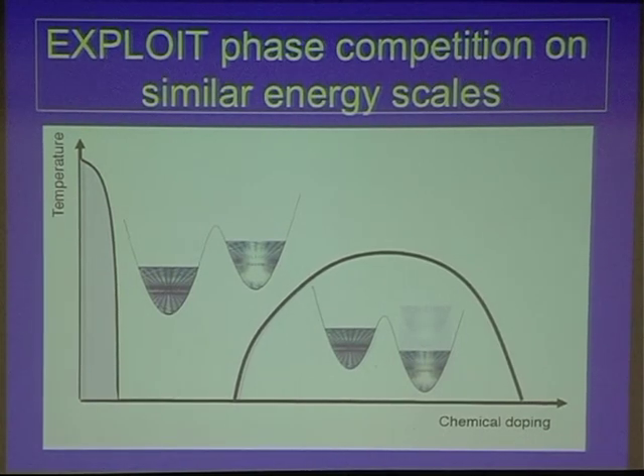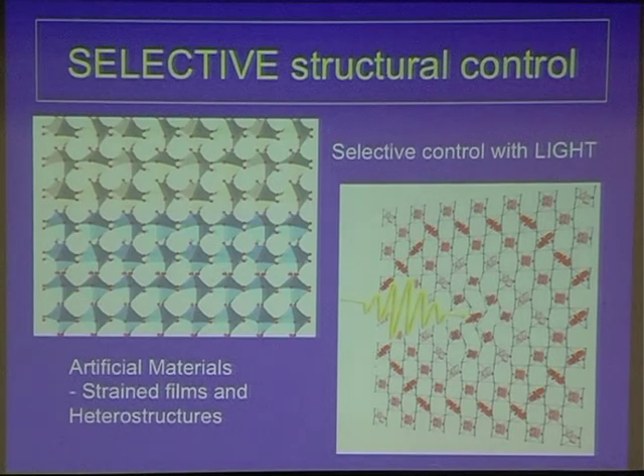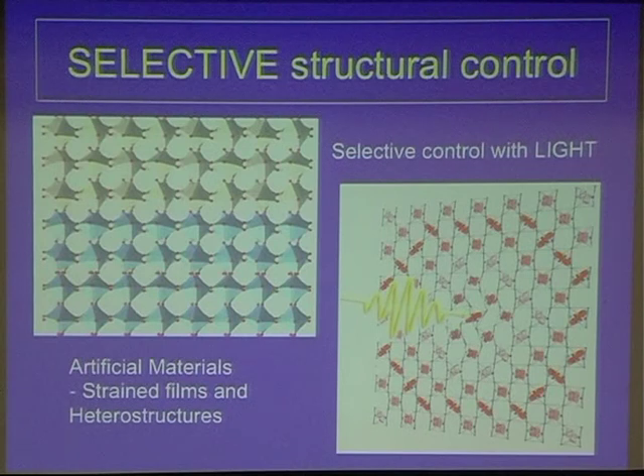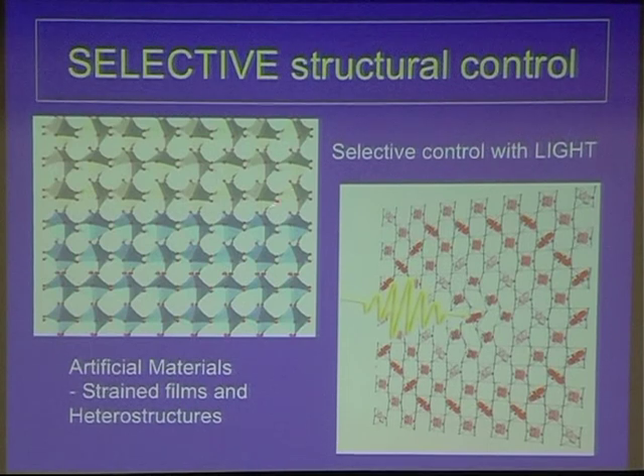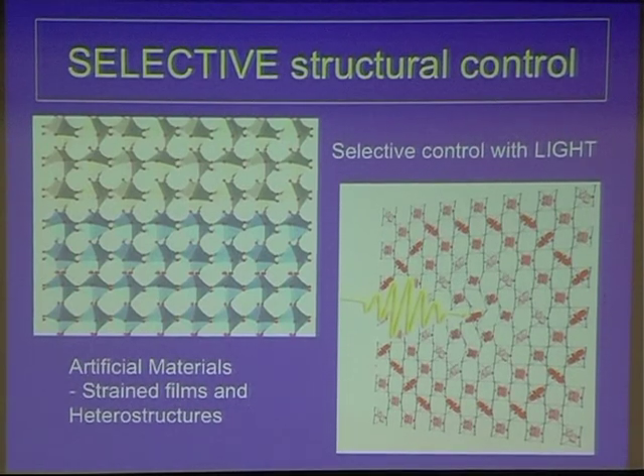How can we do that? We can do that by at least two different routes. One has been already quite a bit explored in the last 10 years, and the other one is an emerging direction. The first route is to build artificial materials by either growing these oxides on a substrate which is carefully chosen so as to induce a strain or a structural constraint in the oxide you are interested in. So this is the whole field of strained films and heterostructures of oxides.